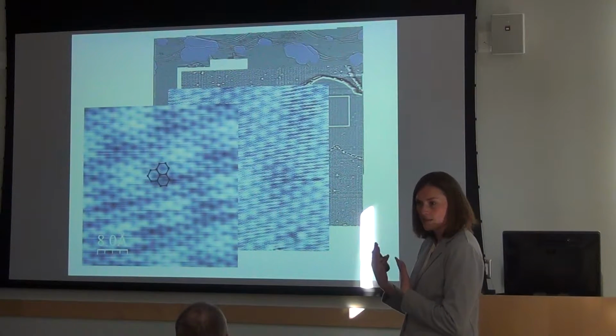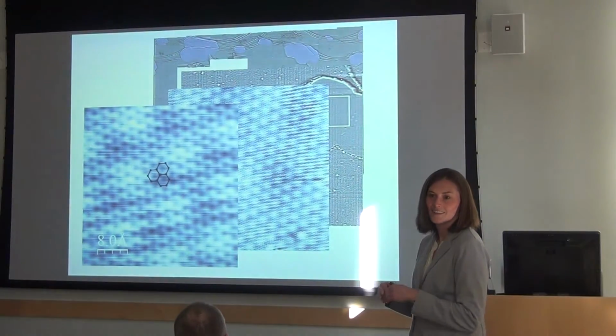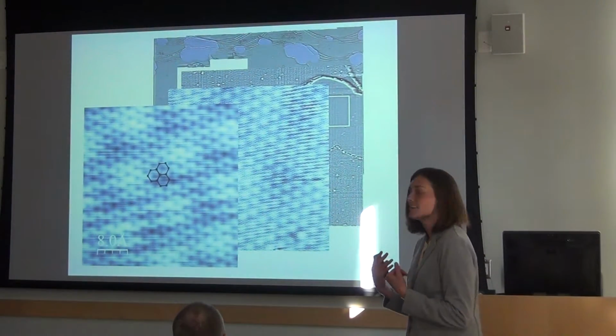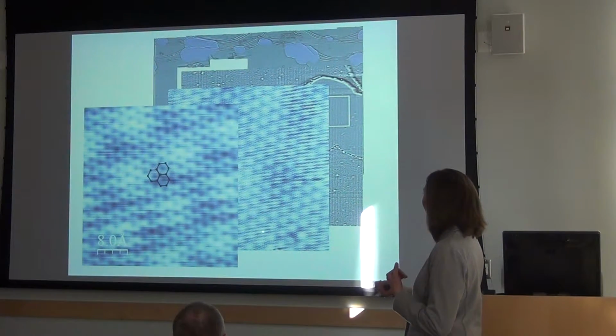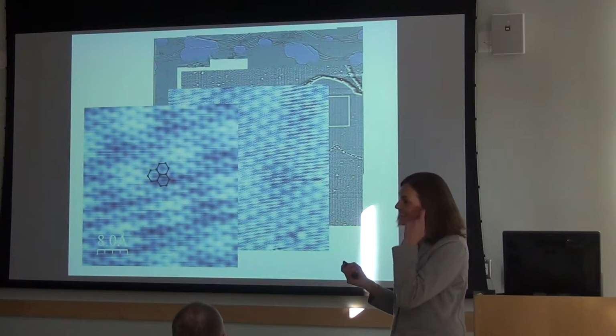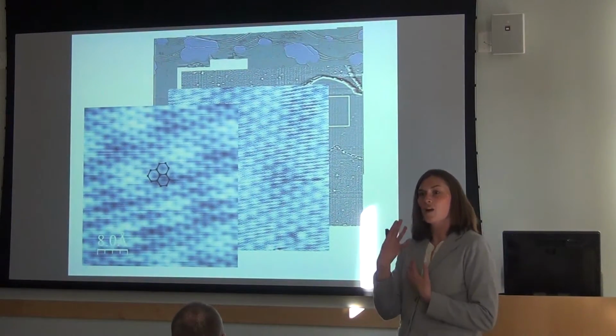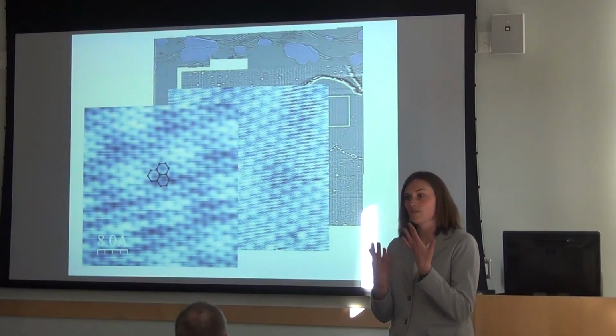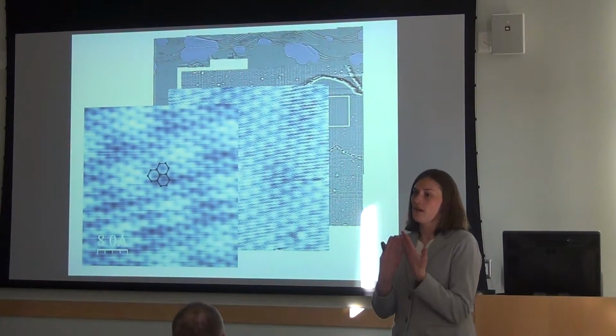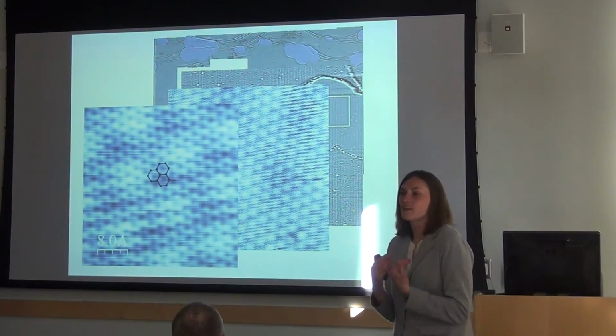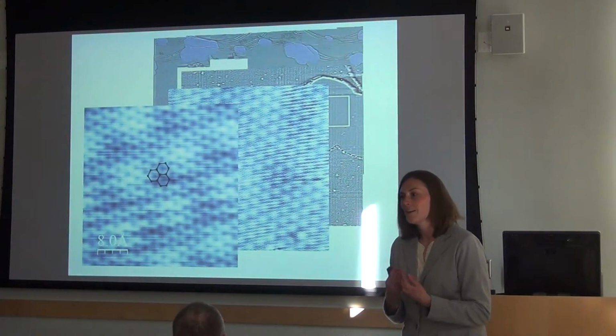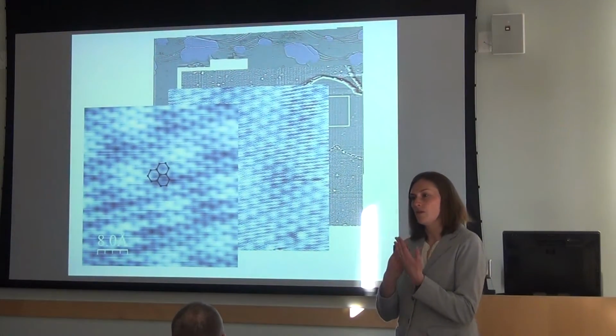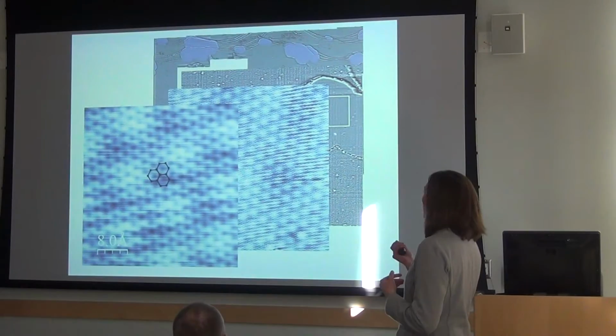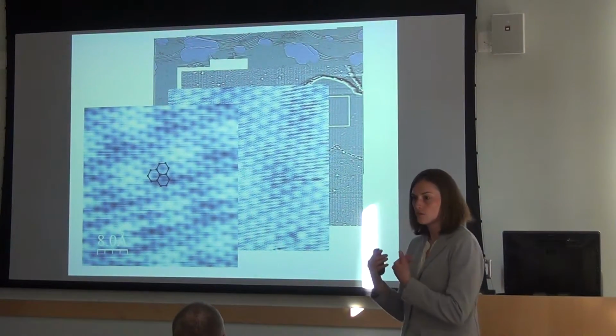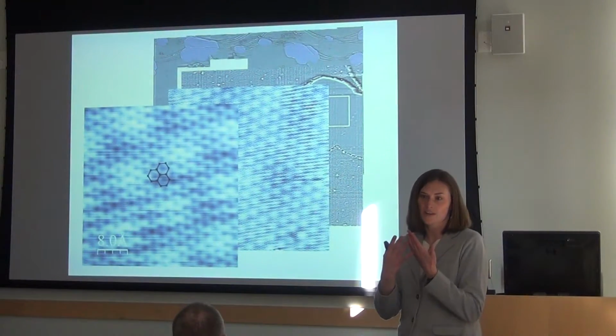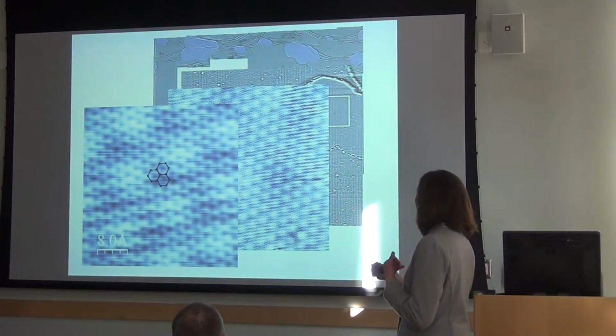Anyone have a guess for what this other pattern is? Copper lattice? It has to do with the copper lattice, but it's bigger, right? You guys see this pattern? It's a Moiré pattern. That's right. So it's a Moiré pattern between the lattice of copper atoms and the lattice of graphene atoms. If you've ever seen two window screens overlapping, you get a secondary pattern that's larger. And that secondary pattern can actually tell you a lot of information about the relative alignment of the two patterns. So if we know what the alignment of the copper lattice is, then we can find out the rotation of the graphene lattice on top of the copper lattice. So that's kind of a fun thing.